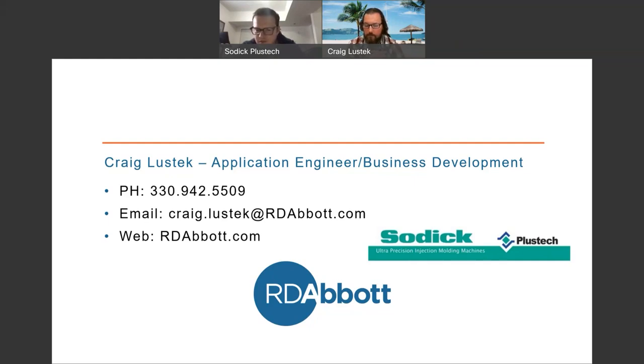Next one, is there a rule of thumb for expected cure time for wall thickness? I always go by the rule of thumb that I was taught years ago: at a set temperature, actual temperature, sorry, of 350 degrees Fahrenheit, it's 4 to 6 seconds per millimeter of cross-sectional thickness. Good to know. I'll say that again, 4 to 6 seconds per millimeter of cross-sectional thickness at 350 degrees Fahrenheit. Okay. That's a good rule of thumb.